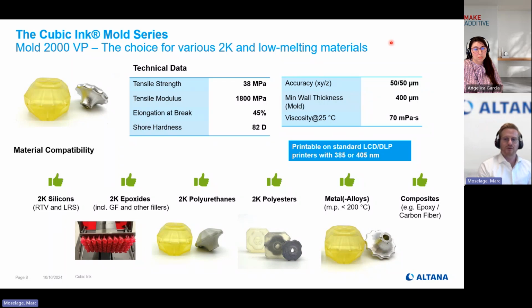Noteworthy is also the viscosity with 70 millipascal seconds at room temperature. This is important because it is easily printable, but also the material doesn't stick so much to the printed part. This is important if you print, for example, tiny holes or channels with a very, very low diameter. If your material is too viscous, it doesn't flow down in appropriate time, so you risk overpolymerization. But this is not the key here.